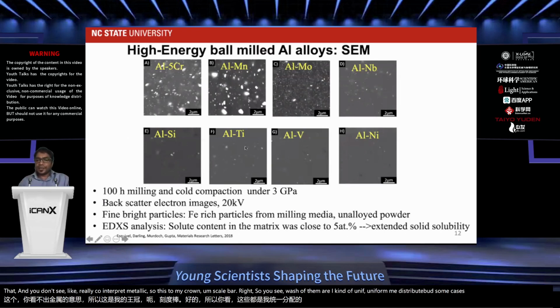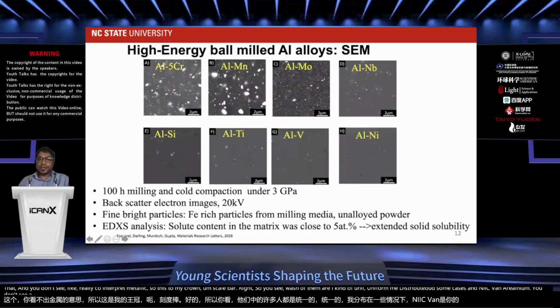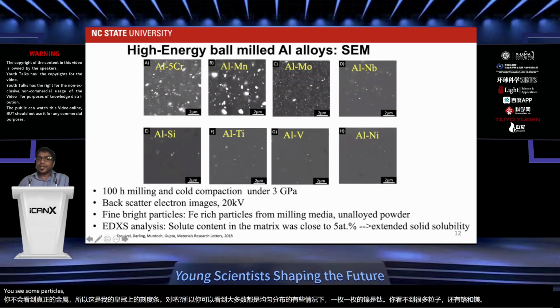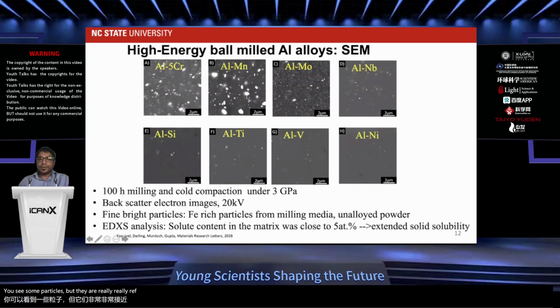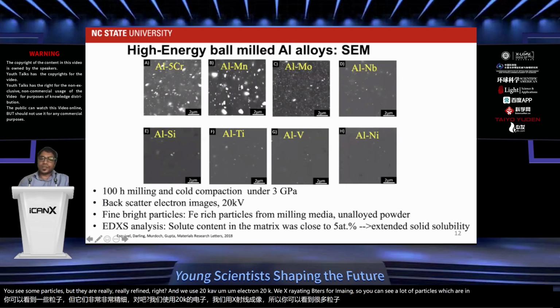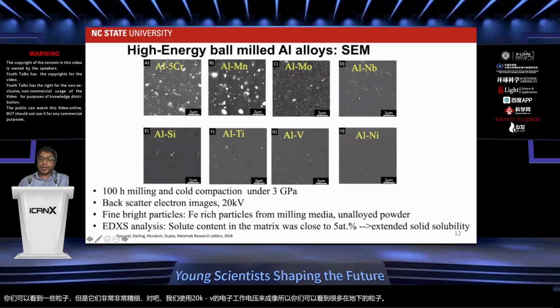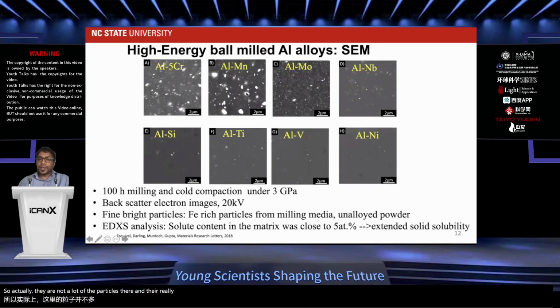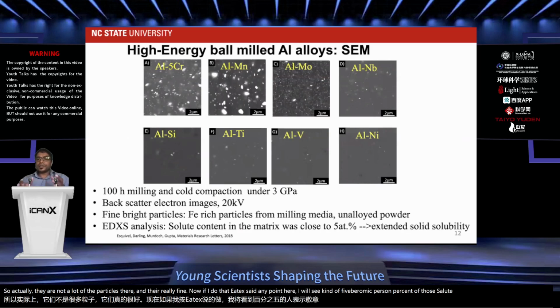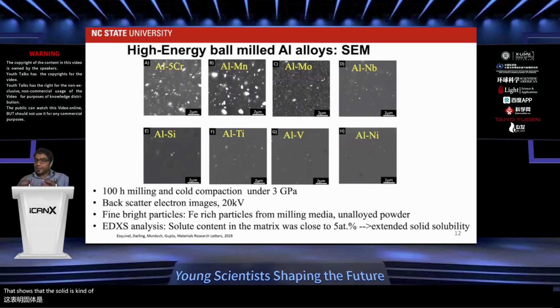In some cases, nickel, vanadium, or titanium, you don't see a lot of particles. In chromium and manganese, you see some particles, but they are really, really refined, right? And we used 20 kV accelerating voltage for imaging. So you can see a lot of particles which are in the subsurface levels too, right? But actually there are not a lot of particles there and they're really fine. Now if I do EDX at any point here, I will see 5 atomic percent of the solute. That shows that the solute is distributed very well within that interaction volume, right?